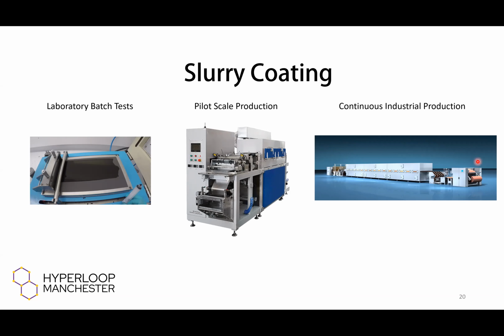But then you go to these really big systems, and these are really cool. And they're big long ovens. It's about 50 meters long, with ginormous spools of aluminium foil and copper foil, and they're doing the feeding and the coating at this end. The material is shooting through to the other end, and I think they do try and aim for like 50 meters a minute. So I think it takes about a minute for material to pass through here and then end up being coated onto these strips, which will then be processed later on in the next steps.